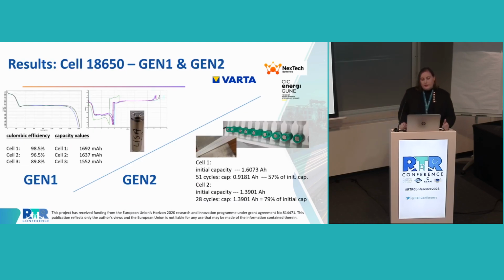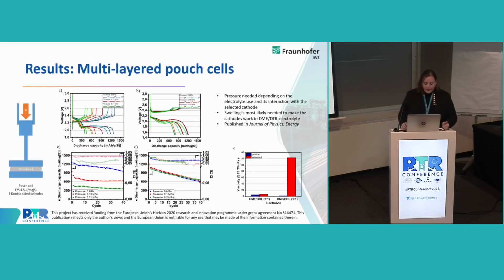Then if we go to the cylindrical cells, here I'm showing you two of the generations that we built. One with liquid electrolyte, which is generation 1, and generation 2 with the hybrid solid electrolyte. Sorry, I cannot show you the long cycling test because they are still ongoing, but as you can see, capacity values are quite promising, and the behavior is almost the same at coin cell and pouch cell level.